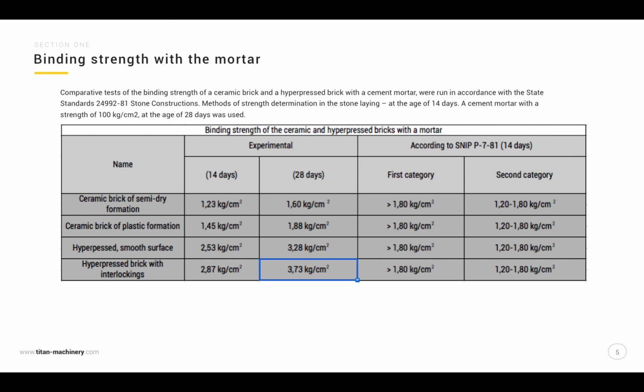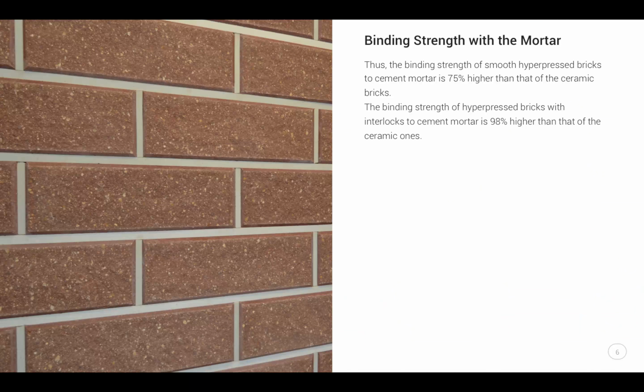Comparative tests of binding strengths of ceramic brick and a hyperpressed brick with a cement mortar were run in accordance with the state standard for stone constructions, method of strength determination in the stone laying at the age of 14 days. A cement mortar with a strength of 100 kg per square centimeter at the age of 28 days was used. Thus, the binding strength of smooth hyperpressed bricks to cement mortar is 75% higher than that of the ceramic bricks. The binding strength of hyperpressed bricks with interlocks to cement mortar is 98% higher than that of the ceramic ones.